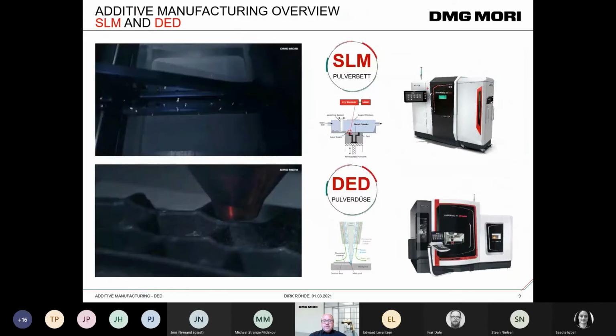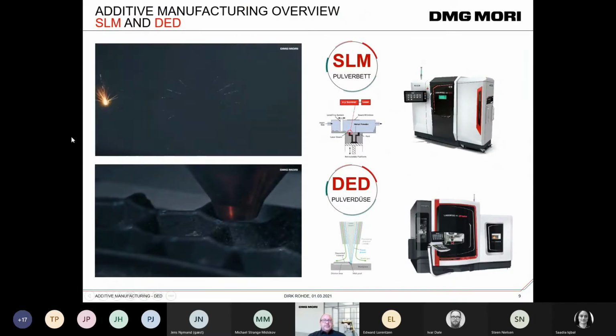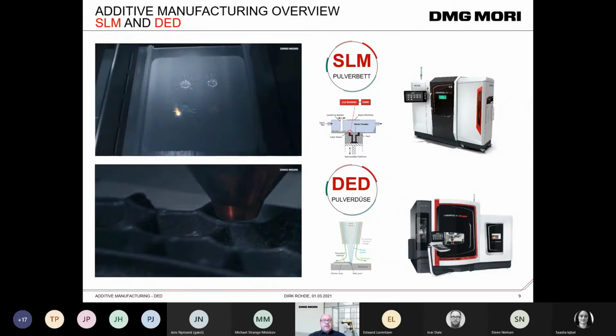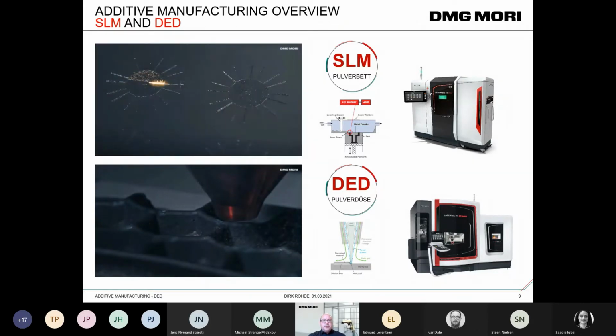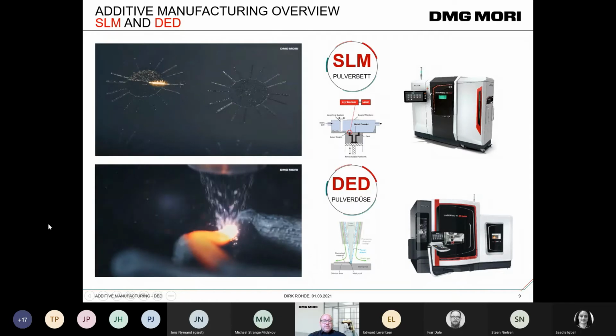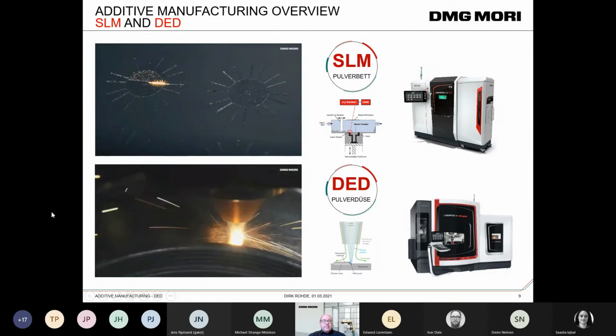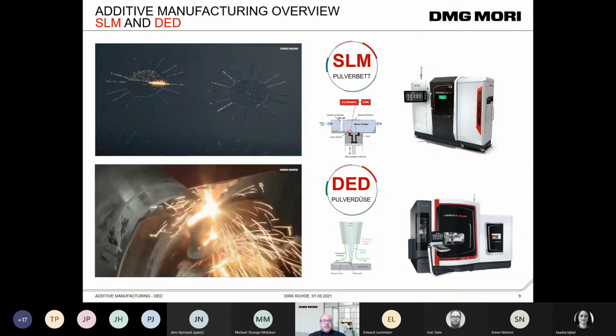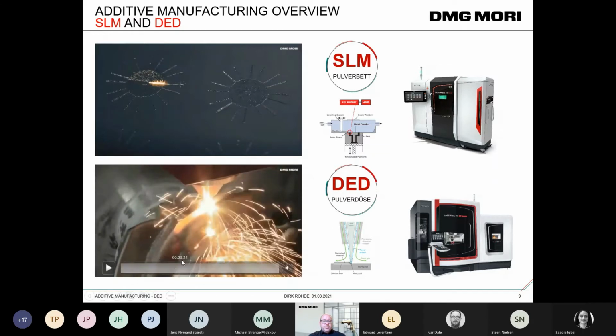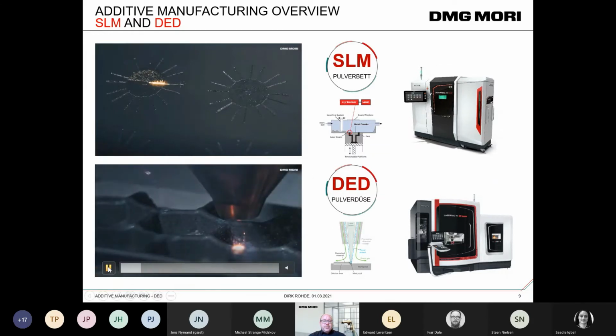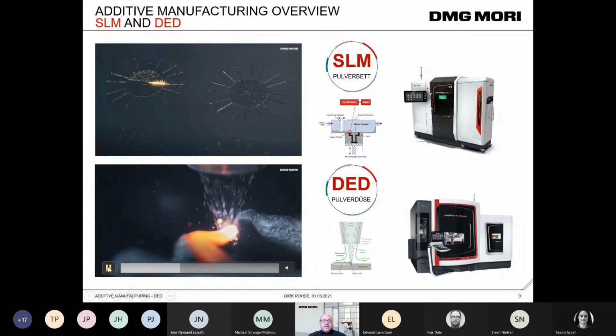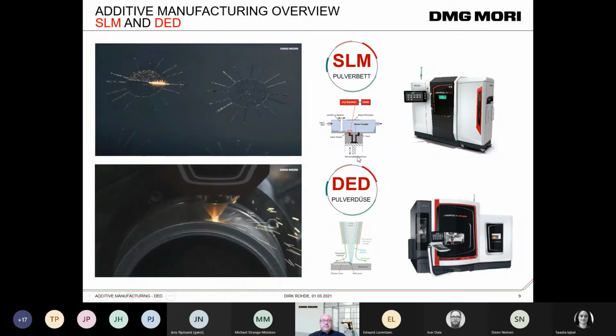Sorry, my presentation was a little bit slow. Here's the typical SLM process where you add powder layer per powder layer, and then you weld the powder with the laser from the top. And this is the DED application where you really have laser welding, where you blow the powder onto the melt pool and build your parts.